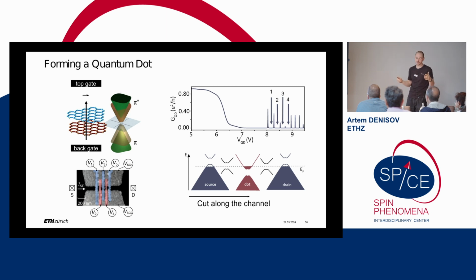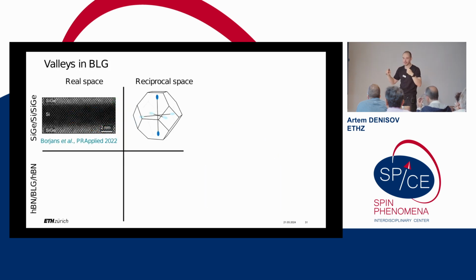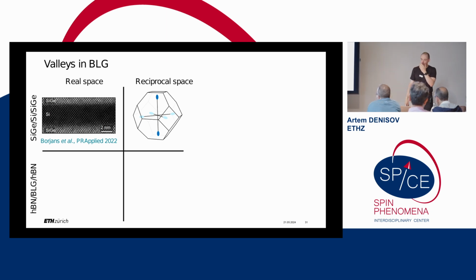So for now, we didn't use the fact that graphene actually has a very rich and exotic spectrum arising from the fact that it has valleys. So let's talk about valleys and then come back to the quantum dots. Of course, graphene is not the only material which has valleys. Bulk silicon has 6 valleys. And when you strain it in a narrow quantum well, as shown here, like a silicon-germanium quantum well, only 2 valleys survive, and these valleys are located in the same direction where your heterostructure is growing atom by atom.